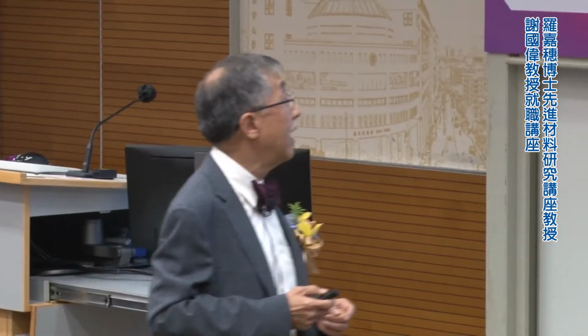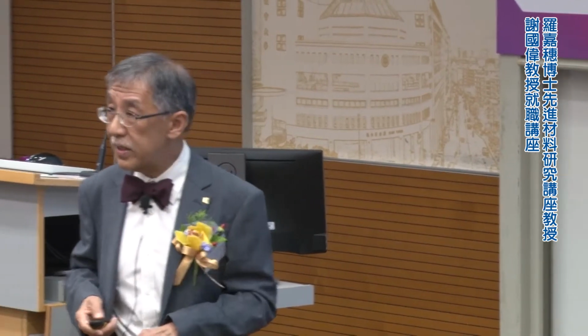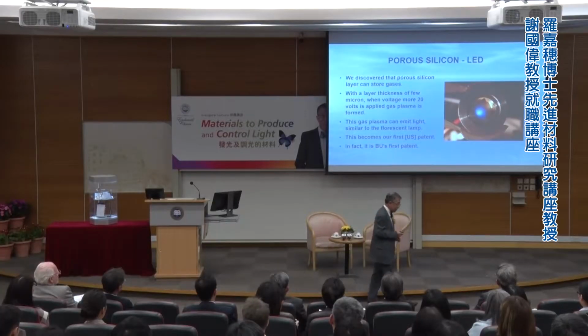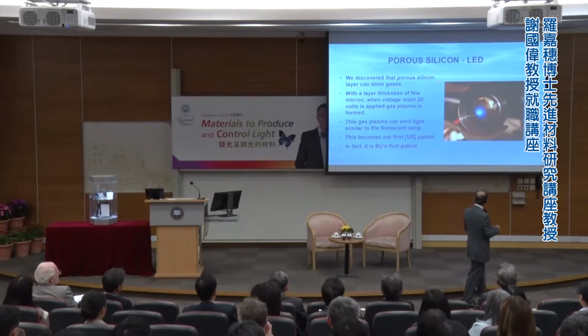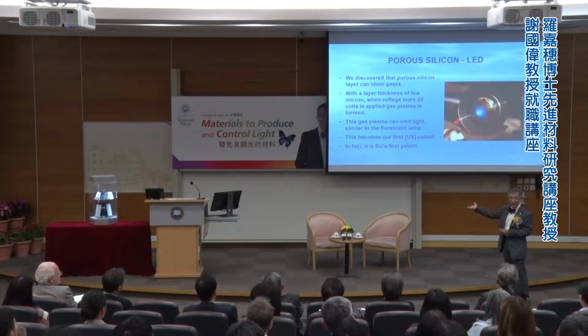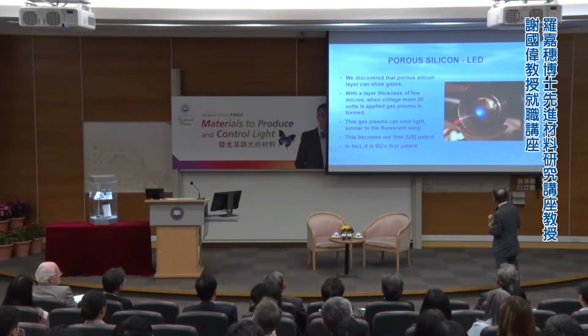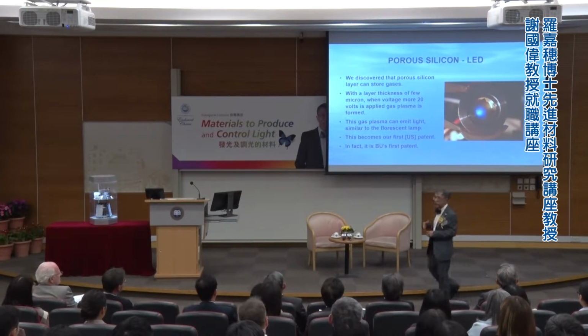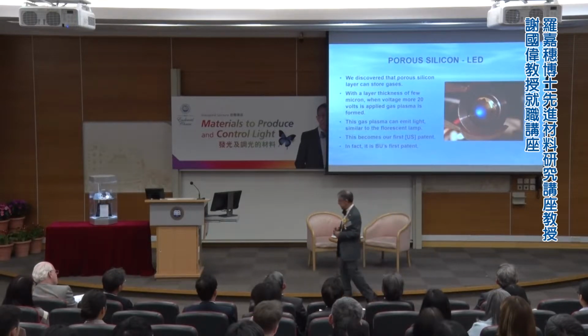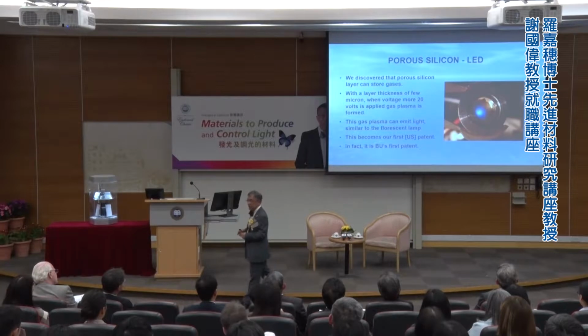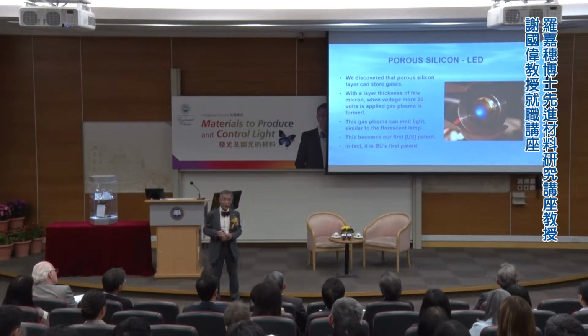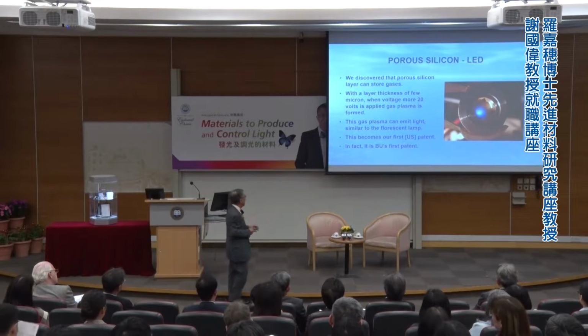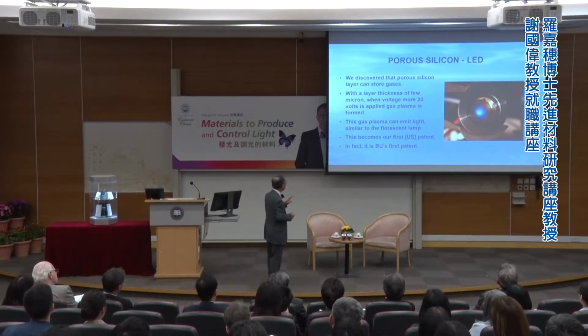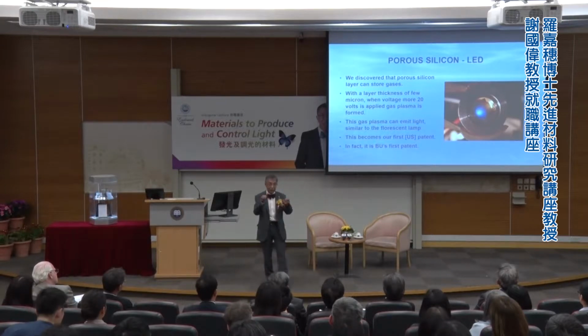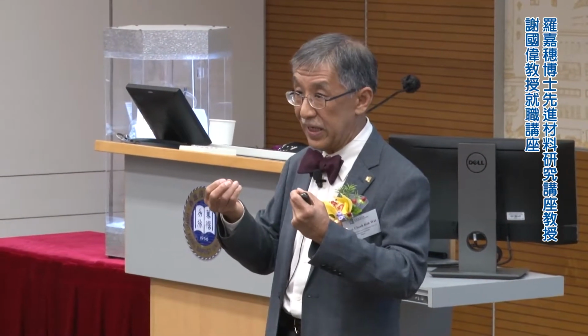We've been trying very hard until around about 1998, 99. It's one of the last projects. You find a project, I say, well, this is it. If we can't do it, that's it, we give it up. And we were successful in getting what we call electroluminescence. That means injecting currents into it to make the light come out, just like an LED. Then once we looked into the mechanism, we realized our luminescence is not so much due to the silicon but the gas itself, because the porosity actually traps a lot of gas inside.